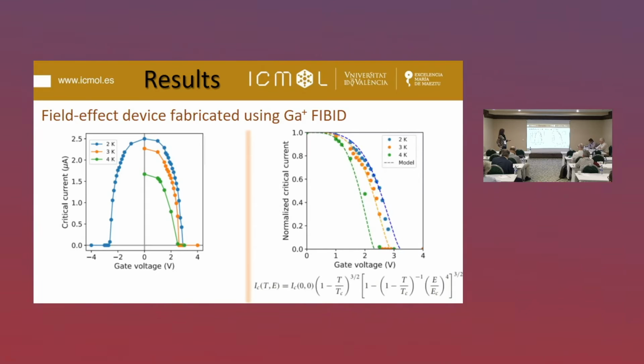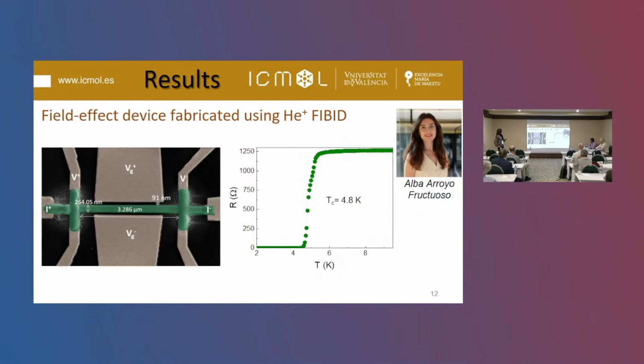And these experimental data are in good agreement with a simple theoretical model based on the Ginzburg-Landau equation developed by our chairman, Vladimir Fomin. So we wanted to extend these devices to a different material, one grown using the helium beam.